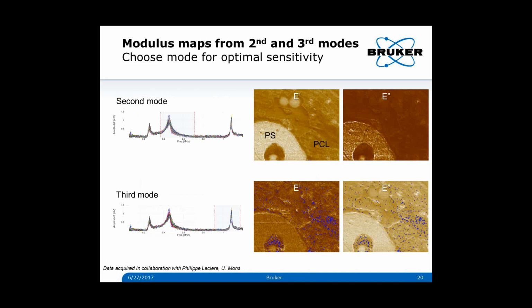You can also do multiple modes at the same time. In this case, we collected a wide enough sweep that we were able to excite the first three eigenmodes of the cantilever in contact. It turned out that the second mode of this cantilever is more sensitive to the moduli in the gigapascal range where the sample is, so it's the best choice for the measurement.